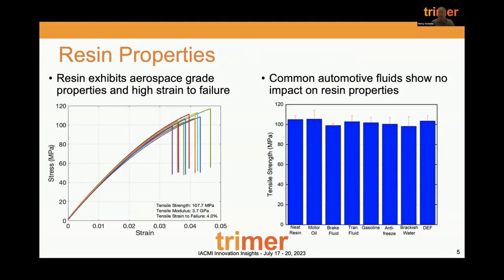It does have considerable elasticity. So on the plot on the left, we have the typical tensile neat resin specimen showing over 100 MPa tensile strength. That's fairly common. Modulus on that particular part is 3.7 GPa, so quite good. And a 4% strain to failure for an aerospace grade resin system is very good.